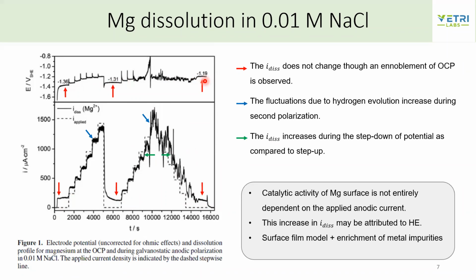It's kind of interesting because earlier they always said that this ennoblement was due to the enrichment of cathodic particles, which kind of increased the magnesium dissolution. But what we see in this data is that the magnesium dissolution current is not really changing. However, there's a change only in the potential, which means it strongly indicates that the surface is modified and has a different chemistry.